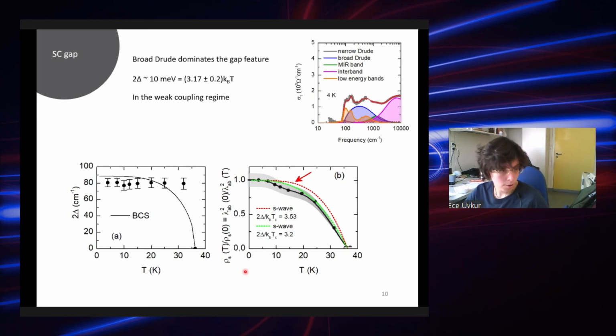Then when we look at our superfluid density, we realize that it doesn't follow this really isotropic s-wave BCS type feature, but rather the BCS constant is a bit small. And also there is some small dip at the europium ordering, which tells you that the system somehow feels the europium ordering, but the superconducting features survive even at temperatures below the europium ordering.